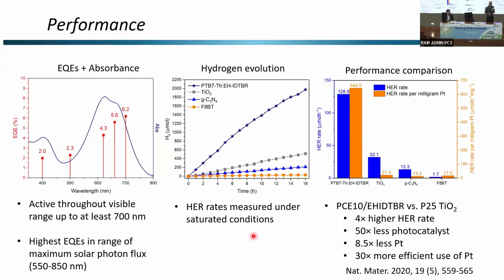So here's another example here. Now, if this was perfectly stable, you would see a straight line. You see this roll over that starts to occur in 10, 12 hours. It looks bad, but we think one of the reasons for this is actually the availability of the sacrificial oxidation agent. So once you deplete it and there's no more left, the rate starts to drop. So this is not only due to degradation, but it's due to lack of the sacrificial oxidation agent. So there's lots to be done. Eliminating excited electrons, I think, is the key for that.